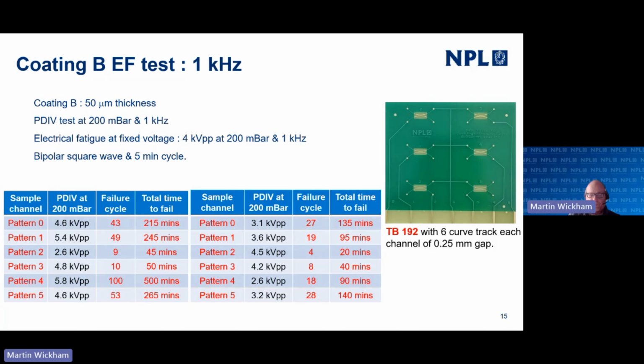Kilovolts peak to peak. What's interesting to note here is that initially the inception voltage of some of these samples is above the electrical fatigue voltage. However, those samples still fail. Sometimes they tend to be longer in terms of failing, but even though there's no PD across these samples, they still fail eventually when we put this signal across them.